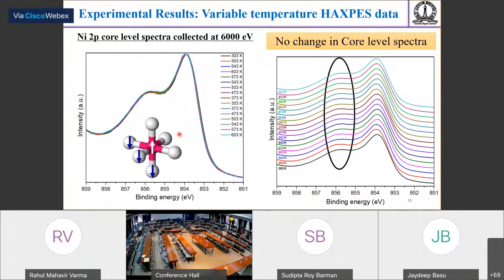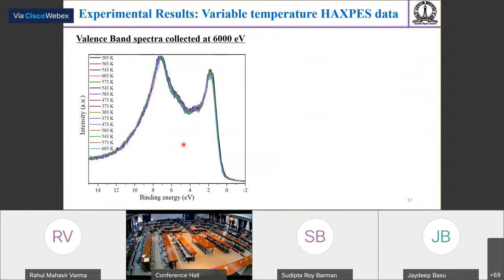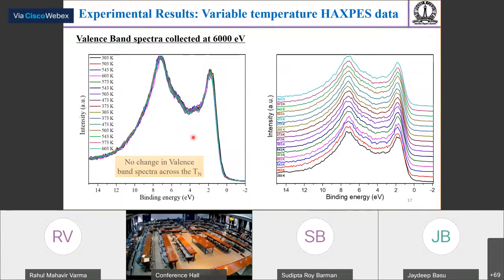So if the explanation given by Kou et al. was correct, we should get a change in either of these peaks across the antiferromagnetic transition temperature, but we are not getting any change. That suggests that even in the paramagnetic state, all the nickel atoms are aligned antiferromagnetically but are free to fluctuate above the transition temperature, keeping the local correlation intact as it is. Similarly, we have collected the valence band spectra and we do not see any changes in the valence band.